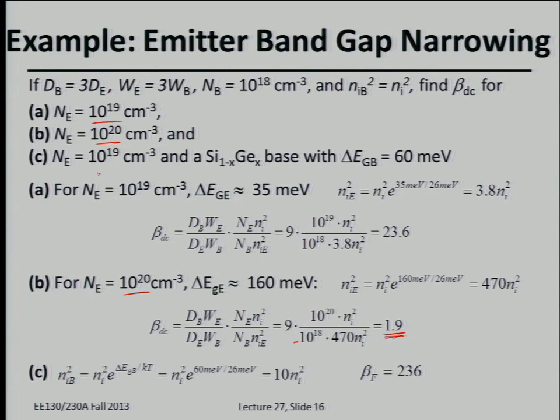But if you go back to a reasonably doped emitter, and just have a silicon germanium base, we have Ni squared increase because the band gap is smaller in silicon germanium by only 60 millielectron volts. We can actually increase Ni squared by a factor of 10. Right? It's 60 millivolts per decade. Ni squared is proportional to exponential of Eg over kT. Anyway, so again, 60 millivolts per decade. So if you have a 60 millivolt smaller band gap in this base region, Ni squared is increased by a factor of 10 in the base region. So you can actually boost beta by a factor of 10.